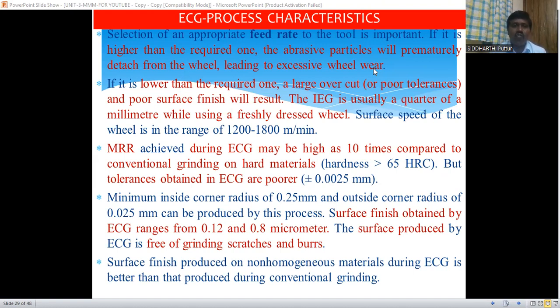The inter-electrode gap is usually a quarter of a millimeter while using a freshly dressed wheel. If you use a new grinding wheel, we have to maintain an inter-electrode gap of a quarter of a millimeter. The surface speed of the wheel is in the range of 1200 to 1800 meters per minute. This much surface speed we have to maintain in the electrochemical grinding process for better conditions. The metal removal rate achieved during electrochemical grinding may be as high as 10 times compared to conventional grinding on hard materials having hardness greater than 65 HRC. But the tolerances obtained in ECG are poorer in comparison to the conventional grinding process.